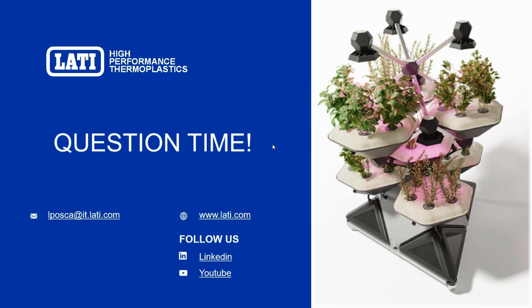Another question, what is the average thermal conductivity in case of the molding process in general? Okay, very interesting question. In case of an isotropic filler, like ordinary metal oxides or metal salts, barium sulfate just to name one, or zinc oxide, they are isotropic. So the number you can actually achieve on your part is more or less 1 to 2 watt per meter Kelvin, and you can rely on this kind of conductivity, never minding the direction in space.